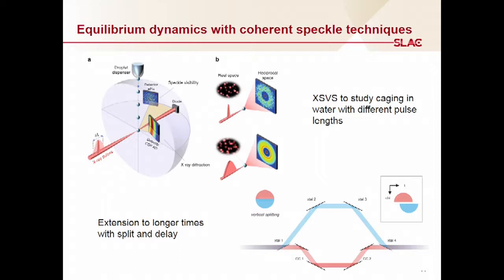And so this experiment, XSVS with the native LCLS pulse duration, is good for less than 200 femtoseconds, which is the range of pulse lengths the LCLS can tune to. If you want to go to longer timescales, however, we do not provide nanosecond pulses. So what they were able to do at XCS was to develop a split and delay mechanism, which allows you to do XSVS with 2 pulses. Those 2 pulses are created when one pulse goes in and is split. One of the pulses is delayed in time, and that time delay can go from hundreds of femtoseconds to nanoseconds. So you can do femtosecond, picosecond, and nanosecond dynamics.